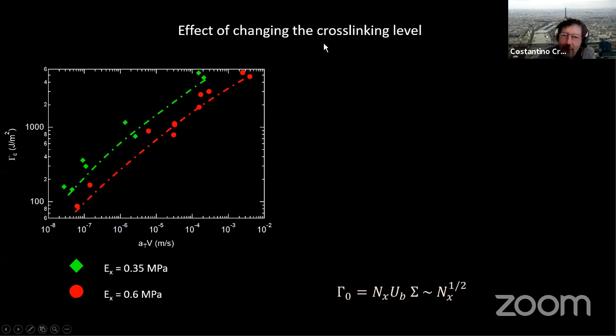Now, another thing that we looked at is this important result from Lake and Thomas, which is the cross-linking effect. If you change the chain length, you also change sigma. So you're actually making chains longer. It should dissipate more energy, but you have fewer chains per unit area. So in the end, actually gamma increases with n to the 1/2. So you would expect the softer material to have a higher fracture energy in threshold condition. We did that with our material with two different cross-link densities, and there's about a factor of 2. You can see that in terms of gamma, we find results that everybody else finds, which is that the softer material actually has a higher fracture energy.